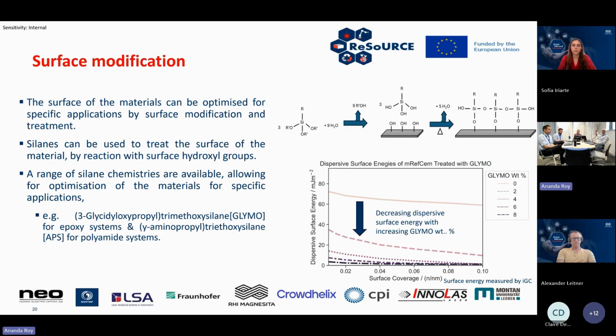So both of these materials have a reasonably high surface energy. So we can also modify the surfaces to enable better integration into whatever application we want to use these materials in. So the model surface modification that we've looked at here uses silanes to treat the surface of the material. And we can create certain functional groups on the material surface that allow it to react into whatever network we want. So for instance, here we've looked at treating the material with a silane called Glymo, which has an epoxy group on it, so it allows it to react well into epoxy systems. We can see that we can modify the surface energy of the materials here by changing the amount of Glymo that we've used to modify the surface.